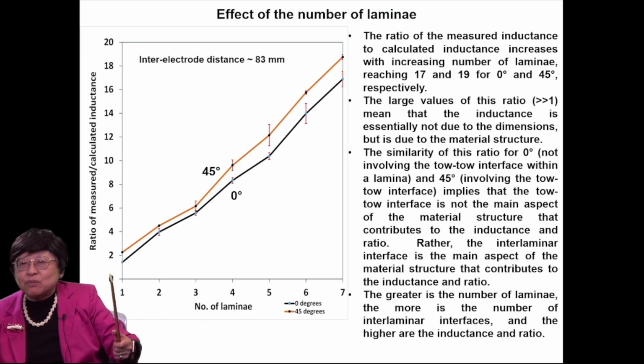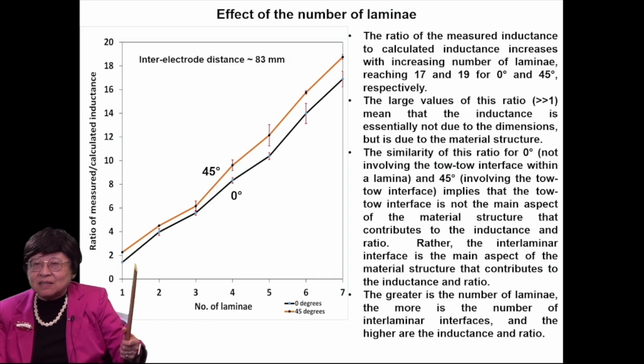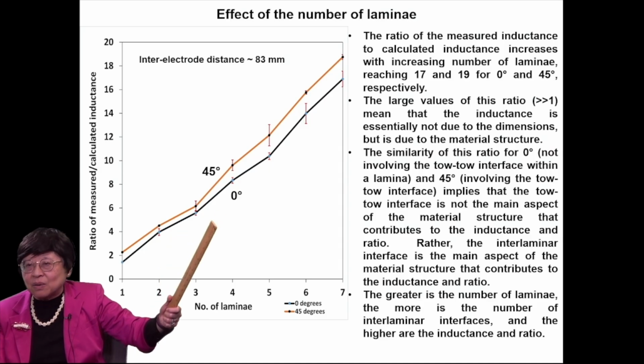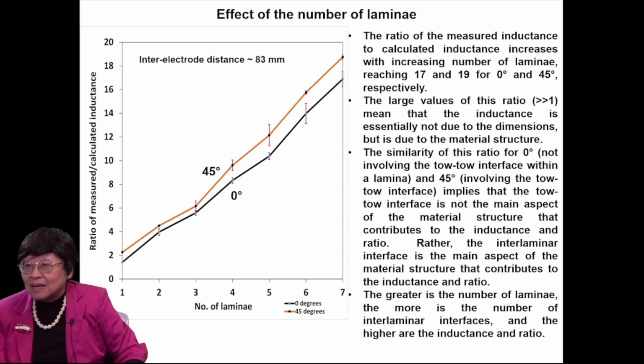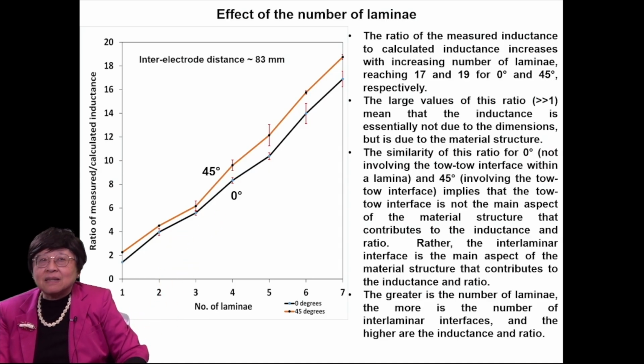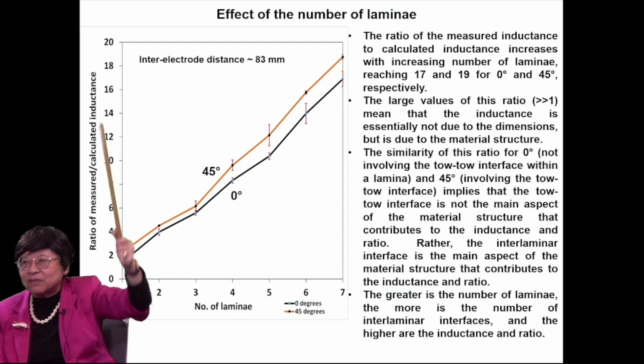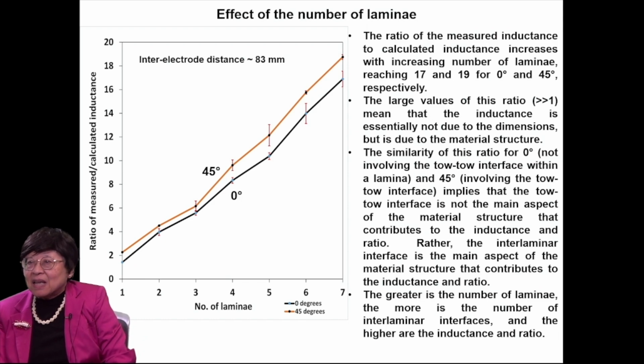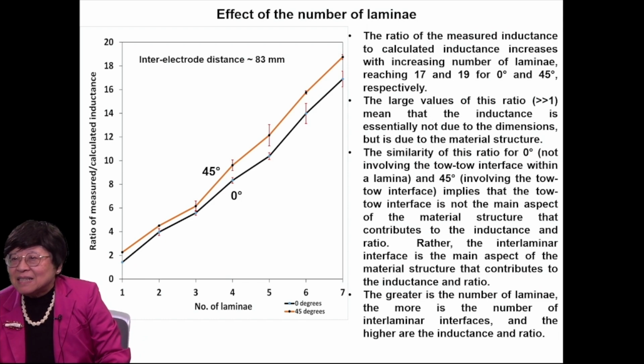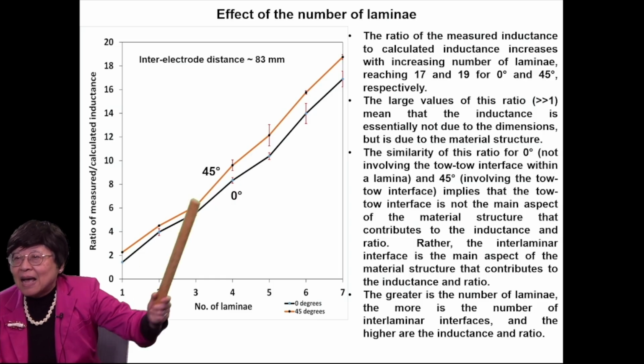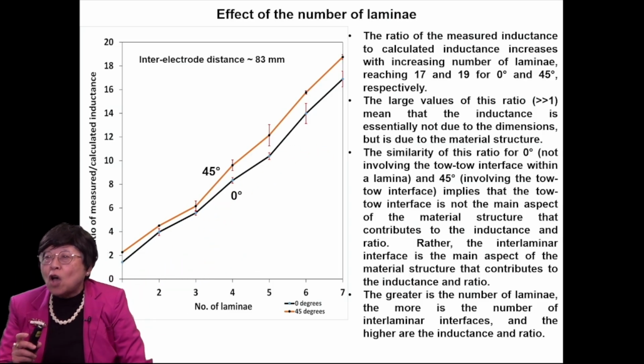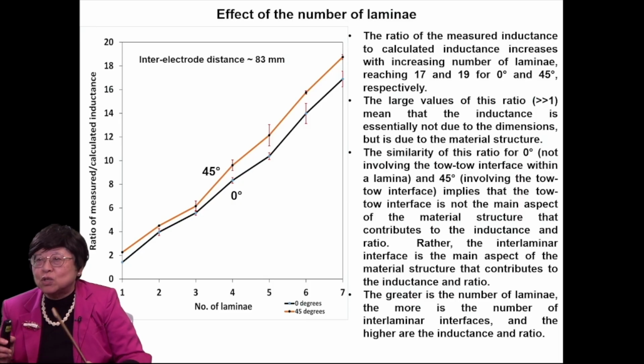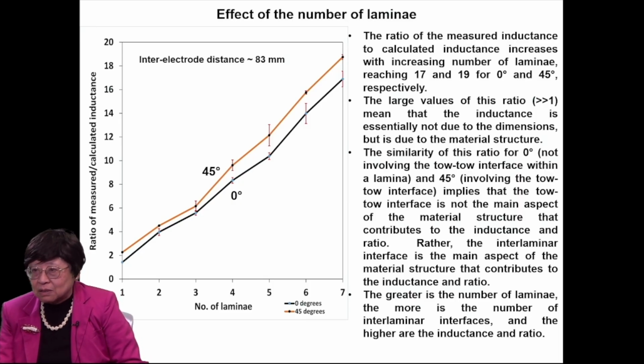And shown here is the ratio of the measured to calculated inductance, and it also increases with increasing number of laminae. And this ratio, note that it gets very high, 17 and 19, gets pretty high. And this large value means that the inductance is essentially not due to the dimensions, but is due to the material structure.